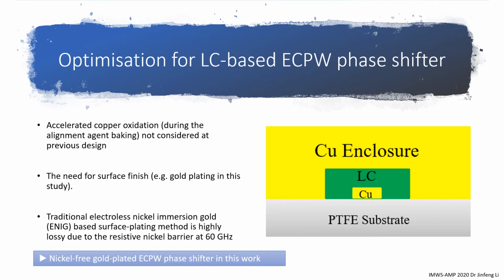For practical performance measurement of my previously fabricated liquid crystal device, higher than expected metal loss occurred because of the accelerated copper oxidation during the alignment agent baking process, not discovered at the design stage. Therefore, there is a need for a surface finish by gold plating in this study, compared with the traditional electroless nickel immersion gold, ENIG-based surface plating method, which is highly lossy due to the resistive nickel barrier. This work reports a novel nickel-free gold plating of an optimum thickness directly on the copper for a low-loss ECPW LC phase shifter at 60 GHz.